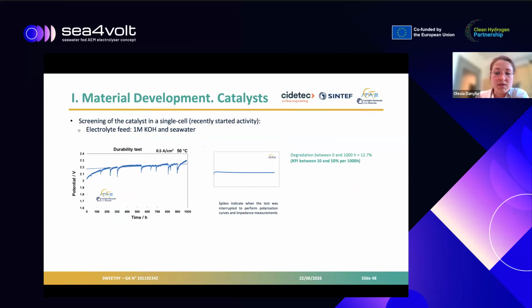One of the latest results is that we started to test our catalyst in seawater at a single cell level. And it's the third partner within this group of partners who developed the catalyst, CNR Italia in Italy. They show that the catalyst that they developed performs well for more than 1,000 hours in seawater, reaching a degradation lower than 15%, which lies well within the key performance indicator that was defined in the beginning of the project. Next slide, please.